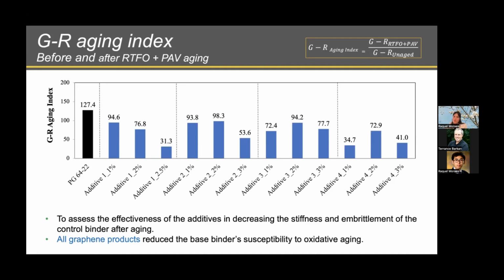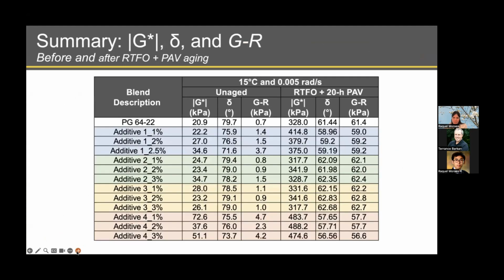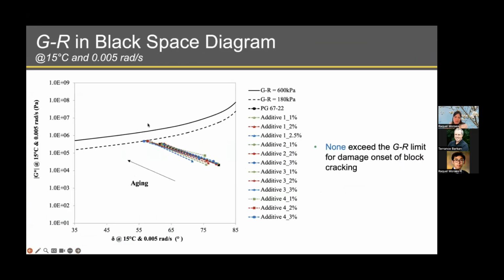And the aging protocol used for evaluation here, as indicated in the beginning of the presentation, was the standard aging procedure that is used for grading or quality assurance of the base binder. 20 hours of PAV aging that simulates between 7 and 10 years of the pavement being in the field. And here we have the overall Glover-Rowe parameters and complex modulus, meaning stiffness, and phase angle, meaning elastic response, of all the binders. And this is what was plotted in this graph shown right here.